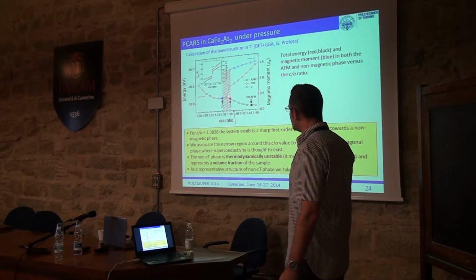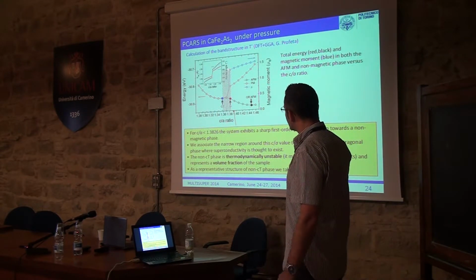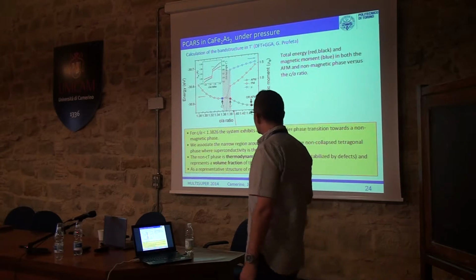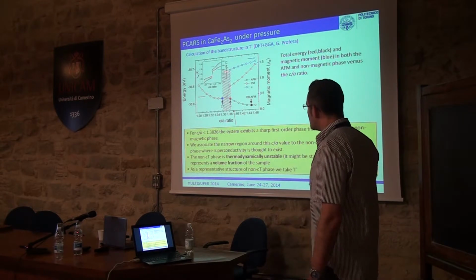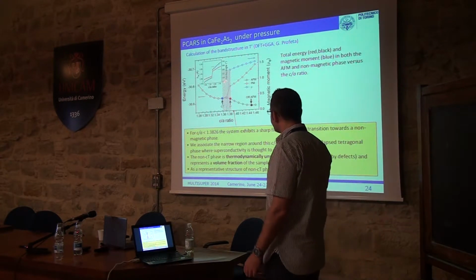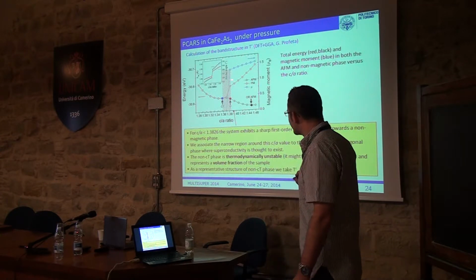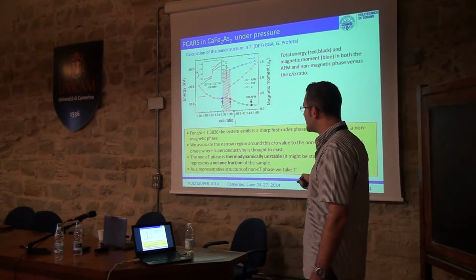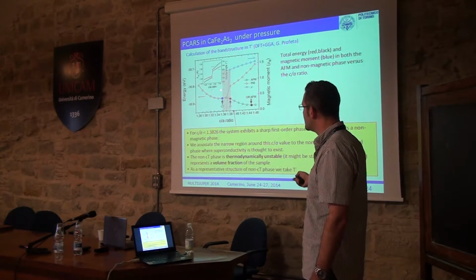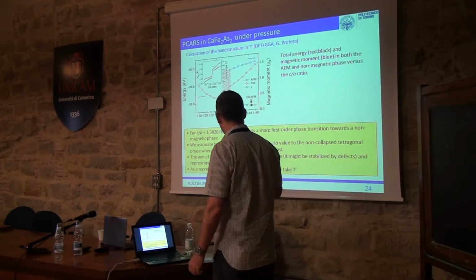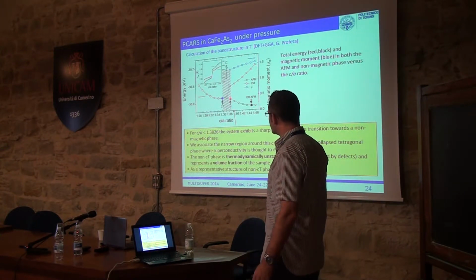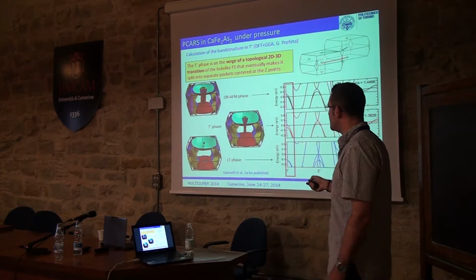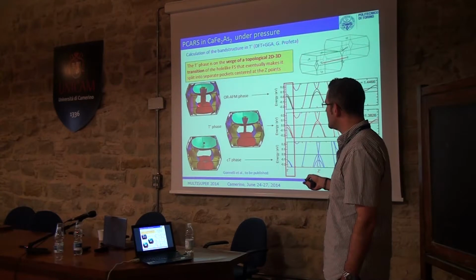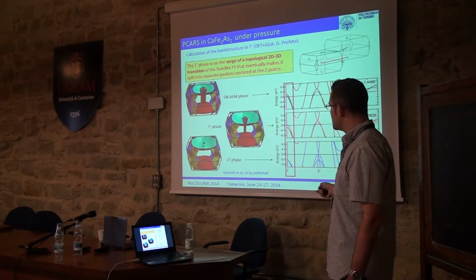But there is also this region which corresponds to the very fast disappearance of the magnetic moment and the transition towards the collapsed tetragonal phase. We believe that the superconducting region lies here, so the structure that hosts superconductivity must necessarily be here. It can be here, it can be there, but it may lie in between. So as a representative of the structure, we took this point here, T prime. And what is the Fermi surface in T prime? Again, we are on the verge of a Lifshitz transition, because this is the antiferromagnetic phase, this is the collapsed phase, and this is T prime.